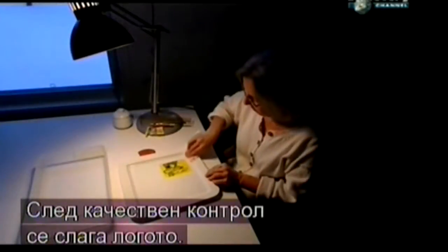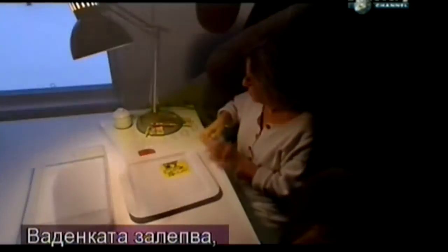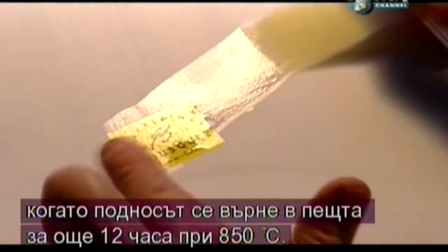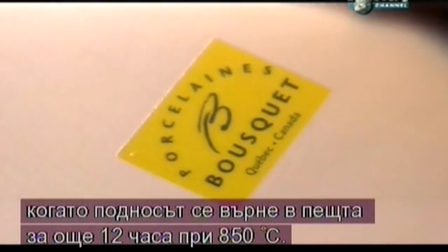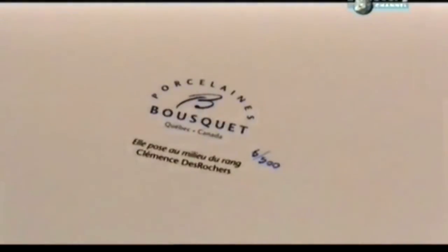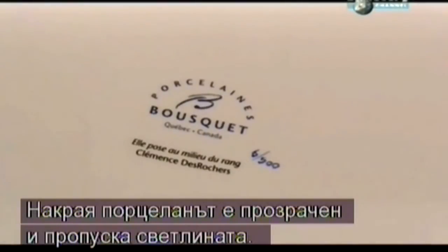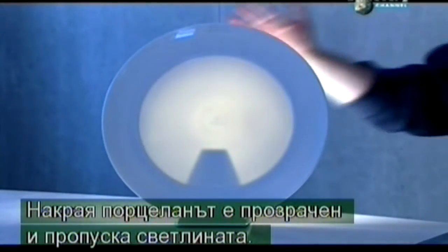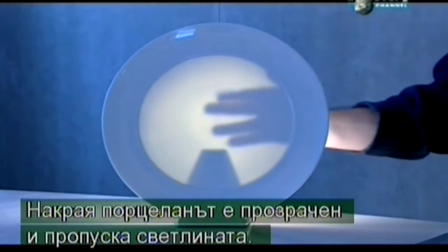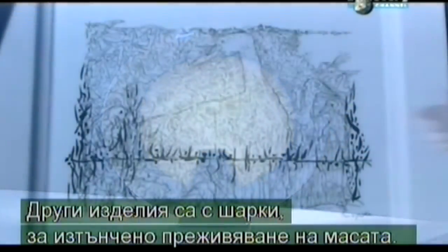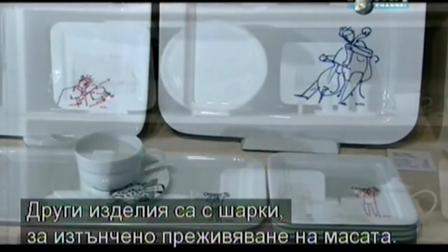After a quality check, the company logo is added. The transfer bonds when the plate goes back into the kiln for another 12 hours at 850 degrees Celsius. In the end, the porcelain is translucent enough for light to shine right through. Other pieces offer more illustrated displays for a truly fine dining experience.